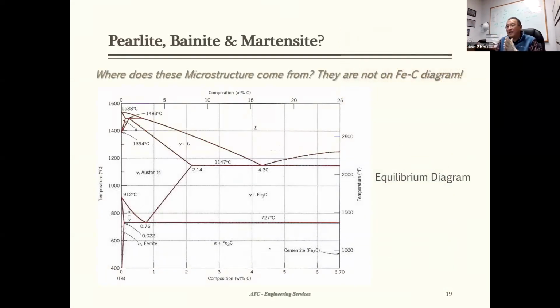Now I've got an issue. You talk about pearlite, bainite and martensite, but on this iron-carbon phase diagram there's no bainite or martensite. So where do bainite and martensite come from? We have to emphasize the iron-carbon phase diagram is an equilibrium diagram, meaning your cooling rate is definitely slow. It's very common in some iron-carbon diagrams to see people label pearlite on there because pearlite is a slow-cooling microstructure, but by definition that's still not 100% correct.